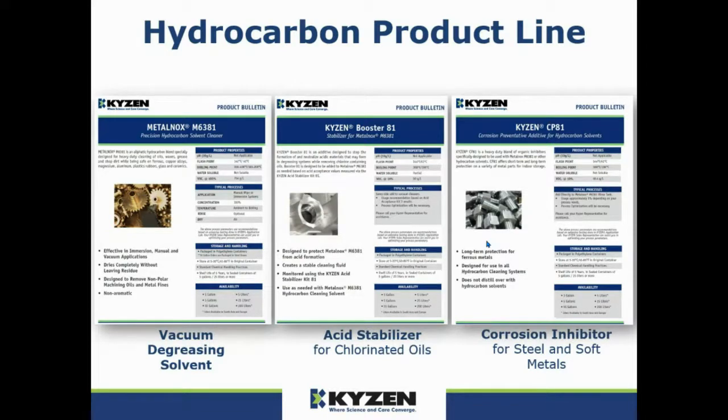Acid can be formed in these machines if there is chlorinated oil, or in some cases, to a lesser degree, sulfonated oils present. This is not like the old solvents like NPB or trichloroethylene. The solvent by itself will not make acid in the presence of heat and moisture, but the chlorine that comes in with some chlorinated oils can. So we do have a product to counter that. It's very easy and it works very well.